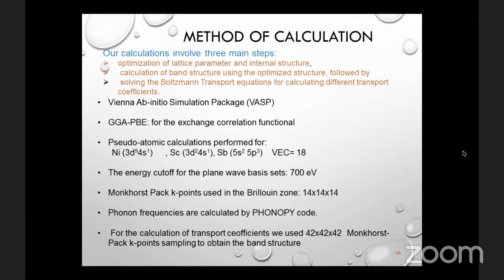The valence electron configurations of nickel, scandium, and antimony you can see here, and the total valence electron count obtained is 18. For optimizing the lattice parameter and atomic positions, we use 14 times 14 times 14 Monkhorst-Pack k-point grids. And the plane wave basis set cutoff was set to 700 eV for all calculations.